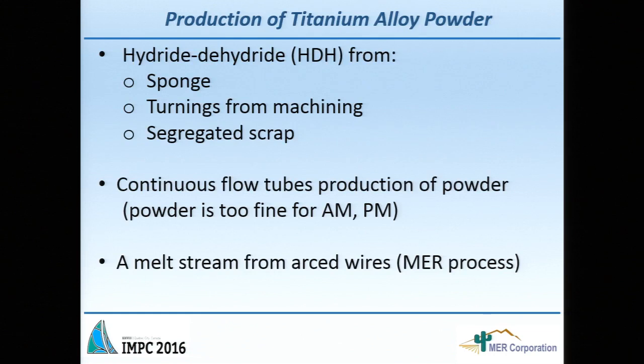So one way is to do hydride dehydride, and that will break down the titanium. And that's done extensively on turning and segregated scrap. And this is the competition, really, to titanium powder: the scrap recycle, and it's a big market for scrap recycle. You can also do hydride dehydride for the sponge, but then you're not going to get the alloy. So this is going to be only applied to high purity titanium. The problem with this powder is that it's very fine. For additive manufacturing and for PM, you need a slightly coarse powder, 25 micron and so on. So this is not very good for the applications.